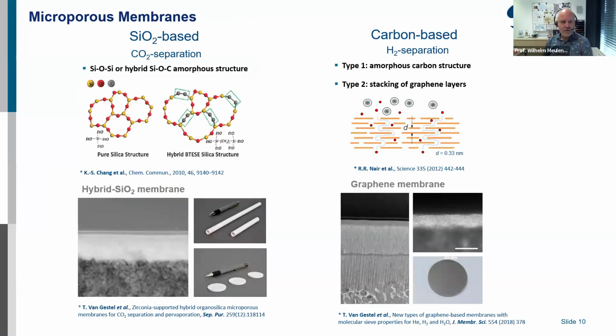So what is known? So now I want to start with the old stuff. In principle, when you look to literature and you look to a microporous membrane, you find some silica membranes. The silica membranes have an amorphous network, and in principle, the name microporous is completely wrong, because we don't have any pores here, because it's in principle a free volume in an amorphous network, which has exactly the size which we need for separation of hydrogen and CO2.